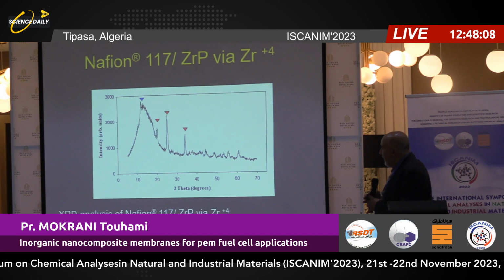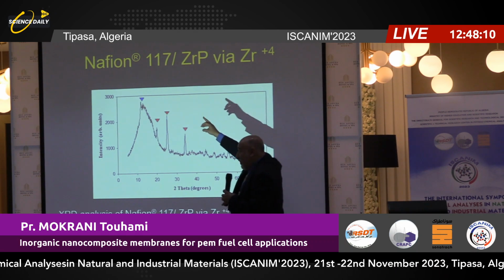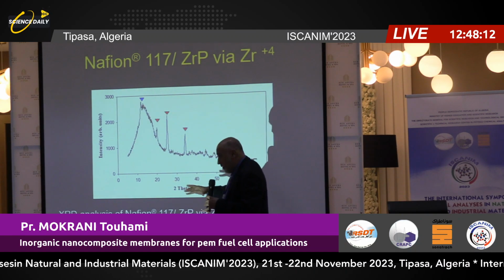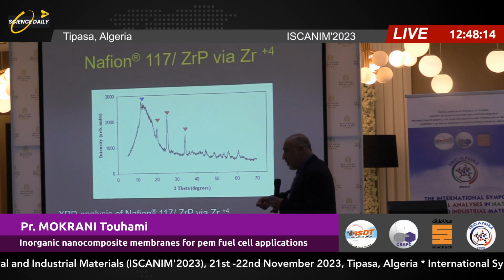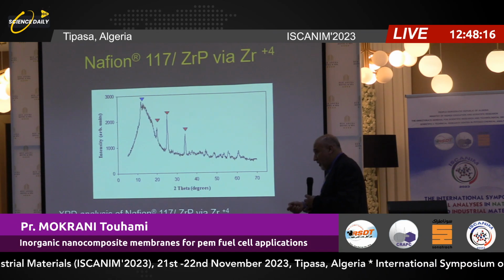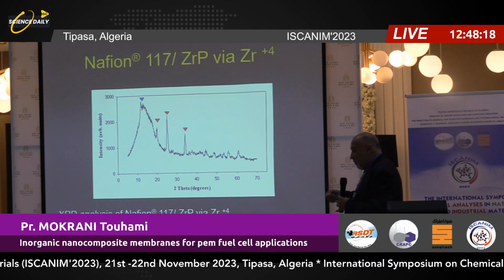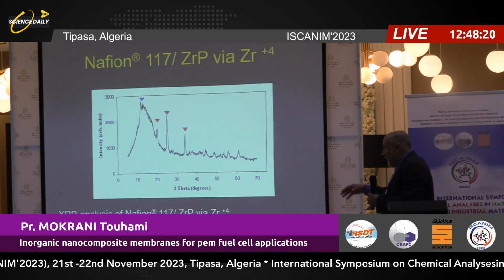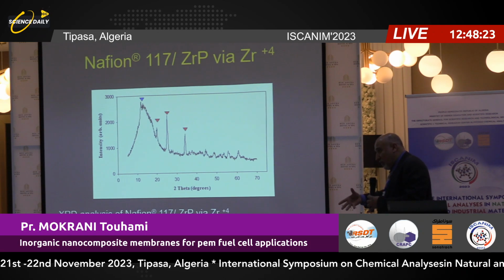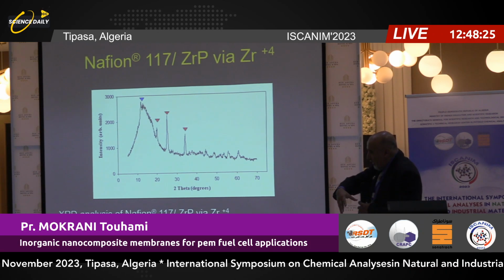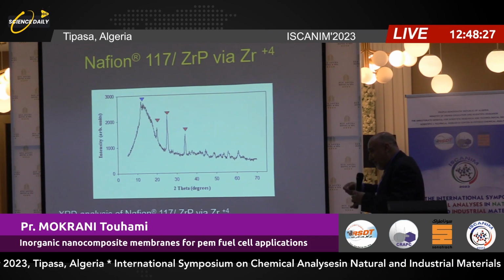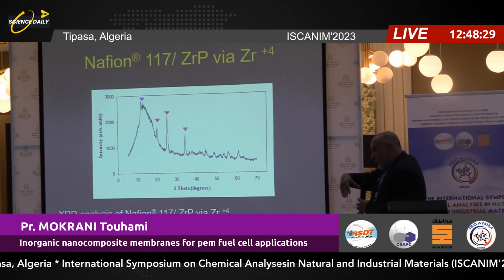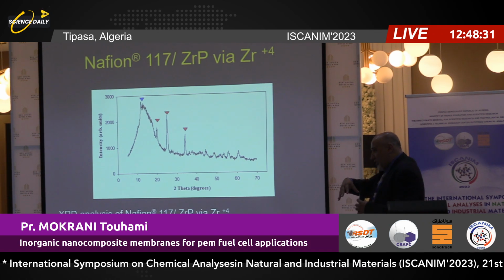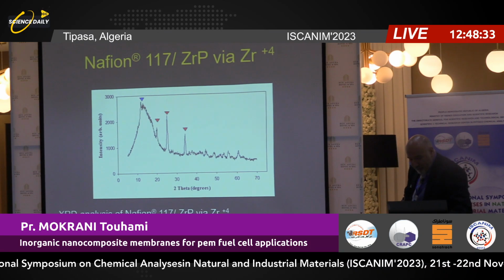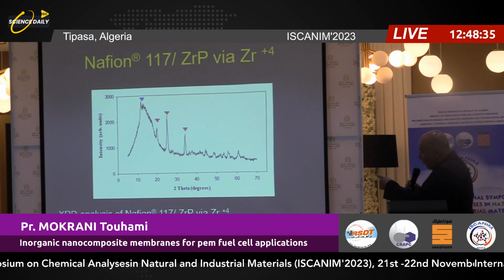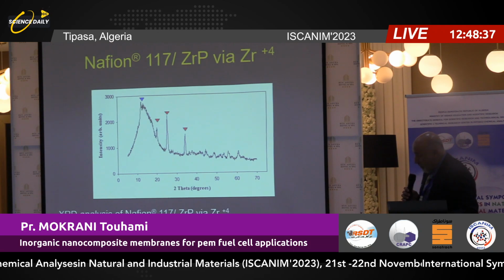This one is very important because we are using the film, Nafion 117, which is the film. And we impregnated it with zirconium phosphate by ion exchange in the film, not recast, because in the previous ones we prepared the powder and we introduced it to the polymer. This one we take the polymer and we impregnate it by ion exchange. And this one is to confirm that we have zirconium phosphate in the membrane, in the film.